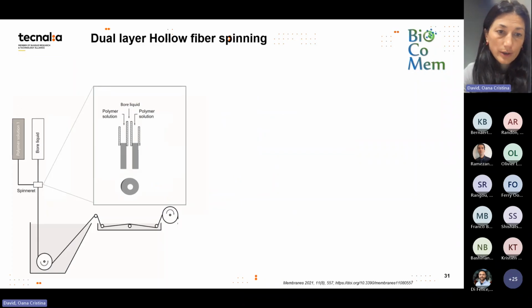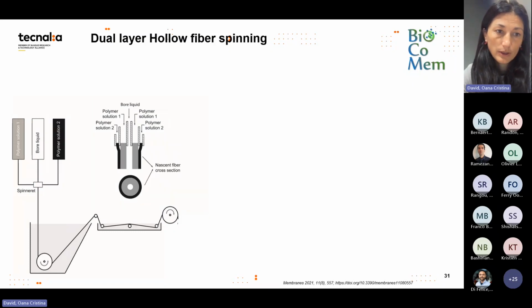So again, going back to the spinning experiments, instead of doing one layer spinning, we decided to do 2-layer spinning. In this case, we form the 2 layers at the same time. It's not a coating process. It's still a non-solvent induced phase separation process of the 2 layers at the same time. But we can use a Pebax polymer with the same chemistry in both layers, but with more polyamide part in the supporting layer in order to prevent pore collapsing due to high flexibility of the polymer chain.